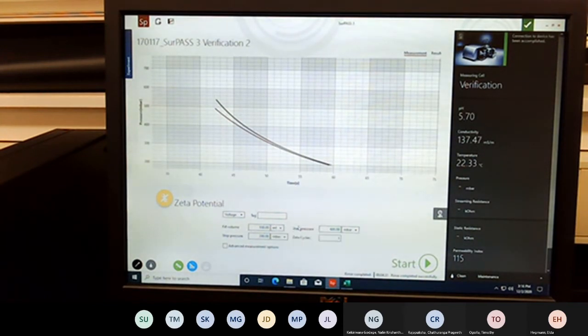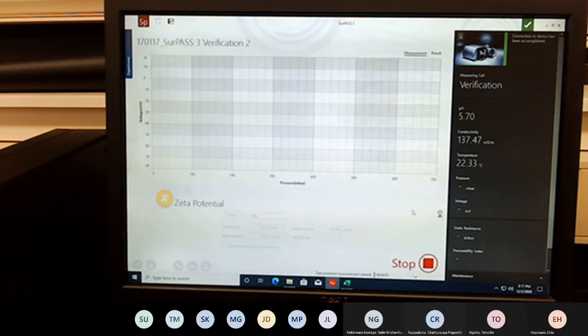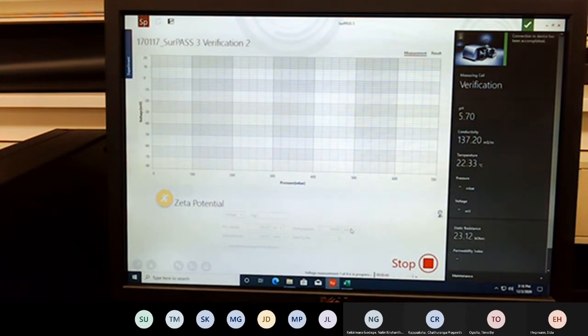Again, all of the parameters that we mentioned before will stay the same. 100 milliliters of fill volume, start pressure at 600 millibar, stop pressure 200 millibar, and let's run this for, say, 4 cycles. Again, the first one we generally don't accept. The second, third, fourth, or fifth would be the ones that we actually take as the values. So we'll go ahead and click start. The instrument indicates here that it's doing the voltage or zeta potential measurement. The instrument's currently draining the electrolytes, introducing it to the system.